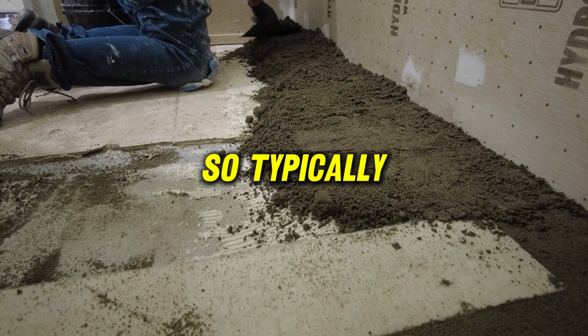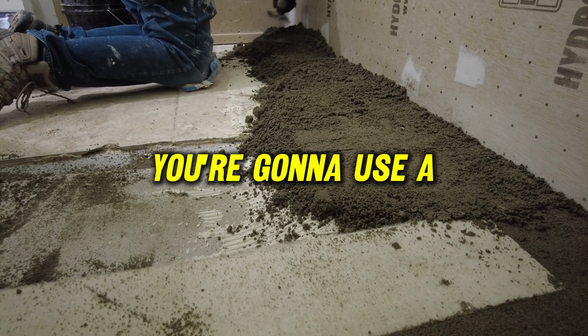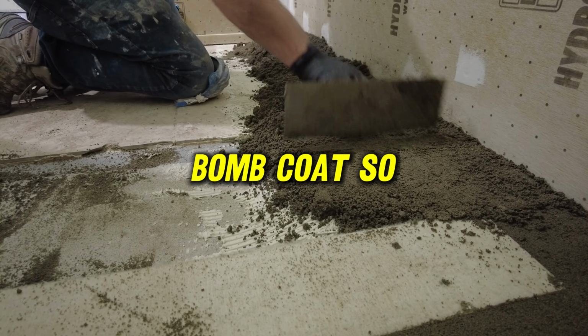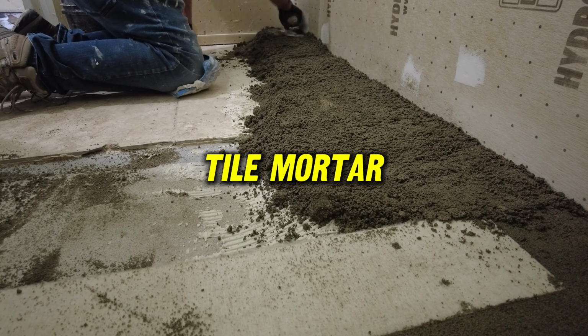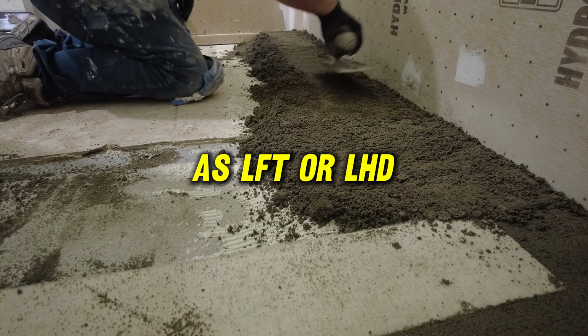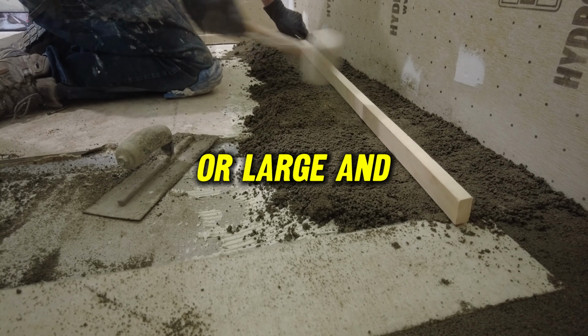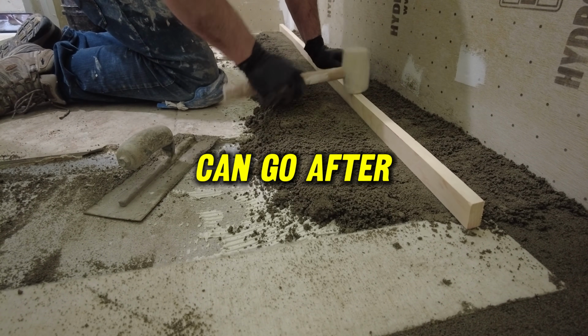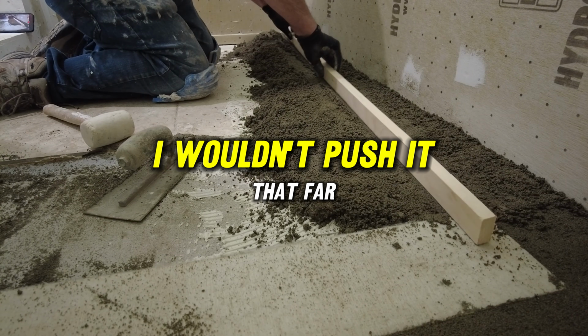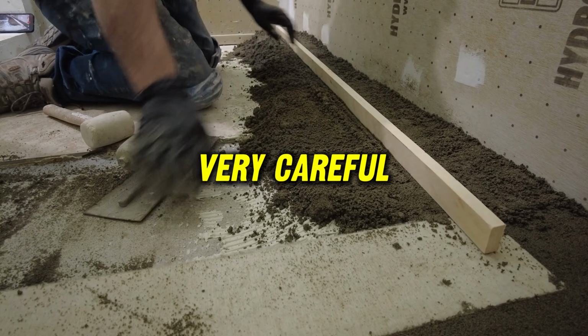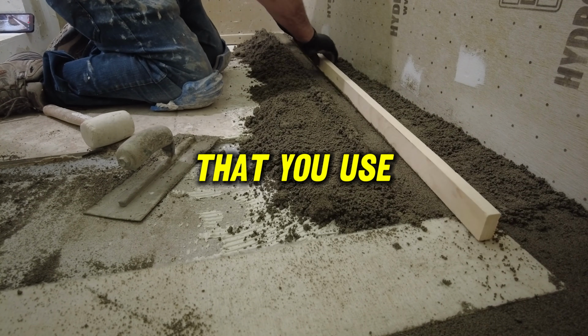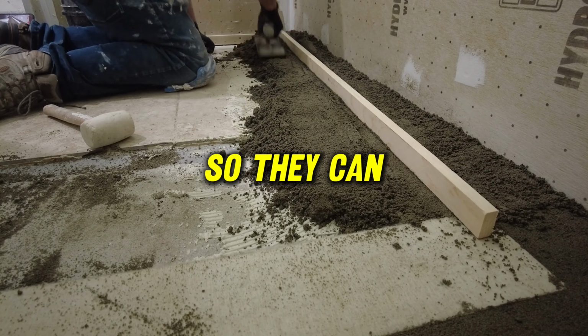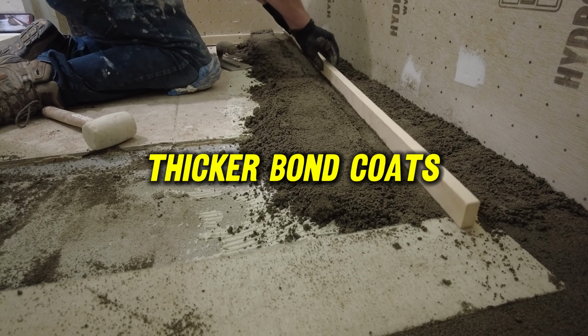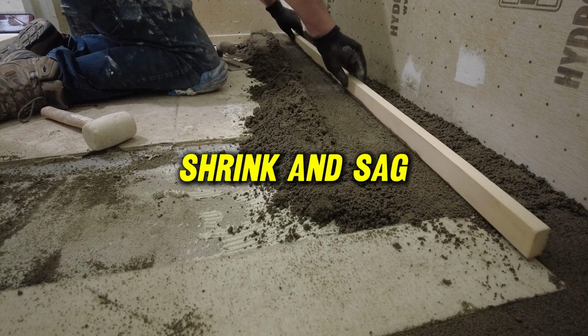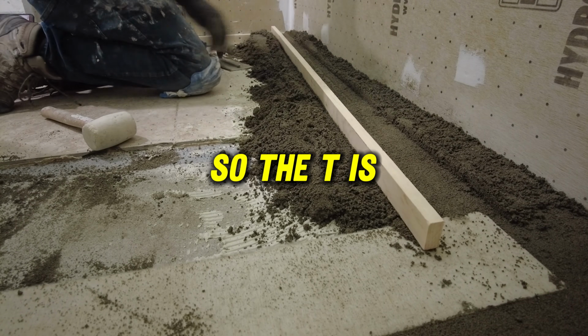So typically with a large tile, you're going to use a bigger trowel with a thicker bond coat. So you want to use a large format tile mortar. They're referred to as LFT or LHT, large format tiles or large and heavy tiles. Those can have thicker bond coats. Some of them can go up to almost 3/4 of an inch. I wouldn't push it that far, but you've got to be very careful when you're picking your mortar to make sure that you use the right one. So they can have thicker bond coats, and they won't shrink and sag. So the T is for no sag.